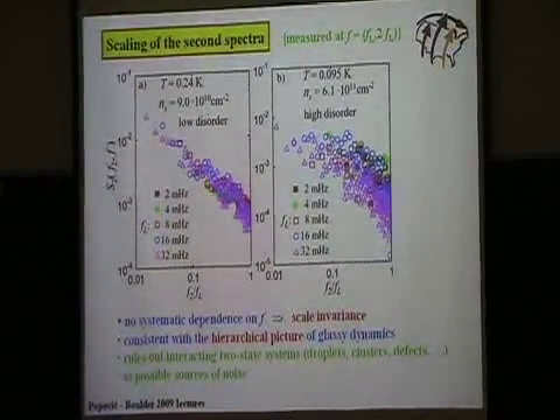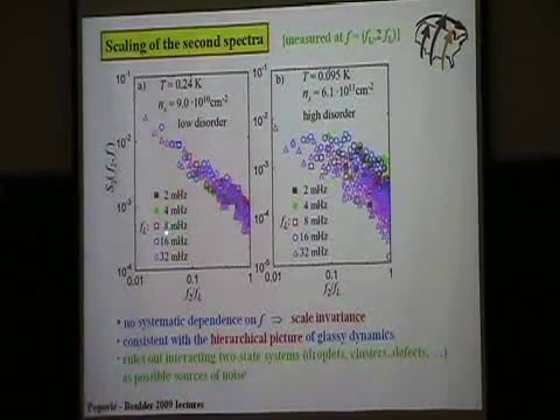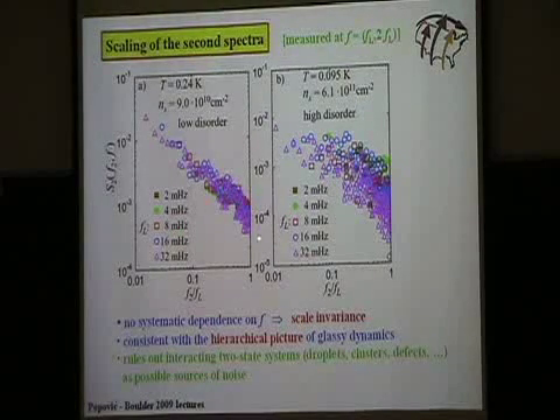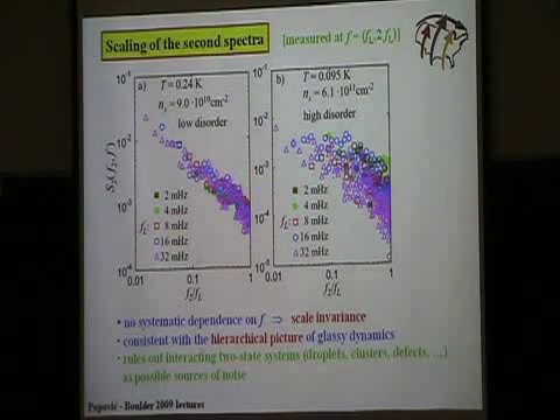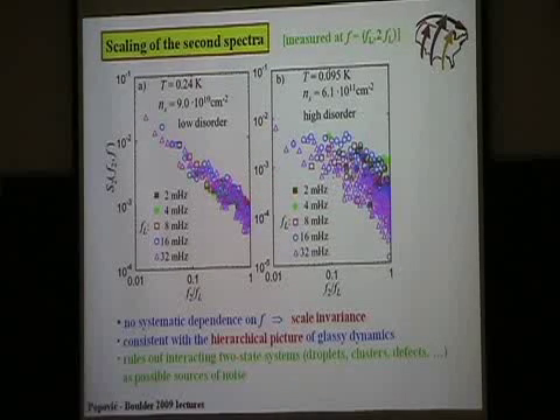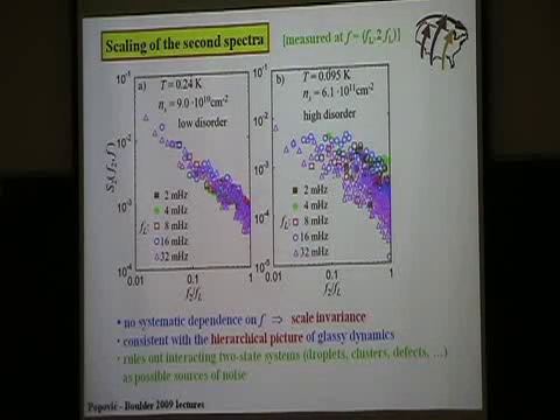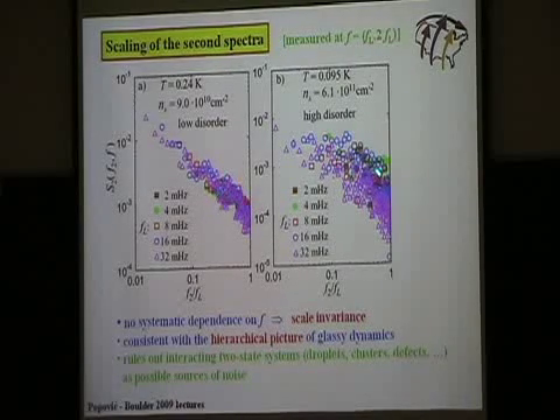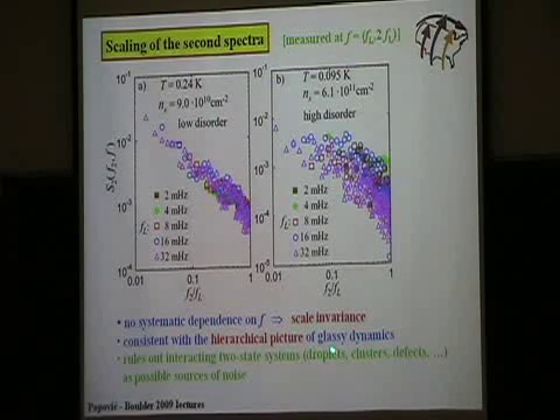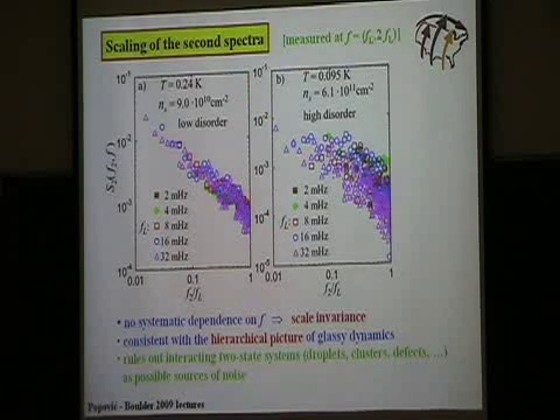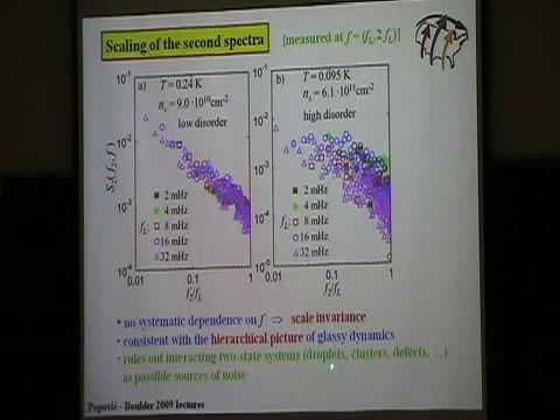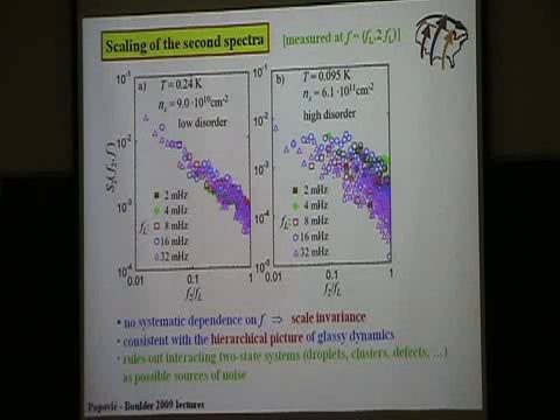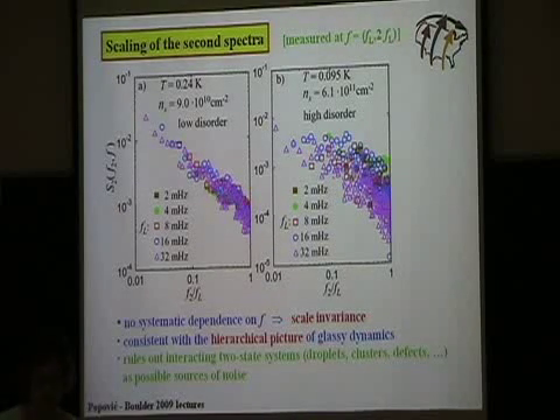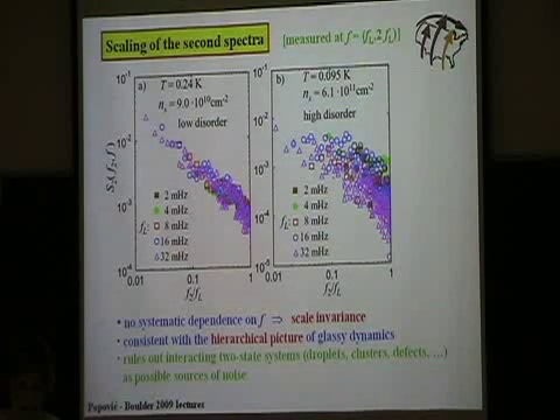Okay, so basically we did this. We calculated the second spectra for different frequencies of the first spectrum, and the data are scattered, yes, because it's noise of the noise, but there is no systematic dependence on the frequency. So we conclude that, just like the situation in spin glasses, this glassiness is consistent with the hierarchical picture of glassy dynamics. So this seems to rule out the various models of interacting two-state systems, droplets, clusters, things like that. And you will see later that the situation in cuprates is different, if I have time for that.